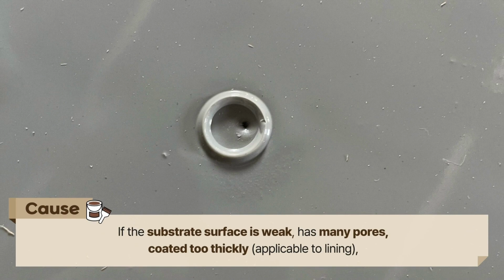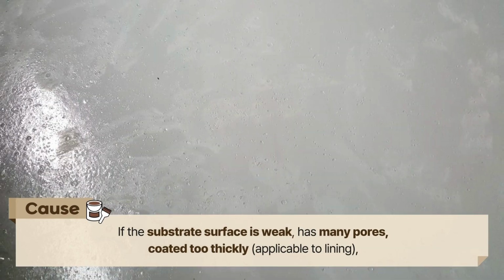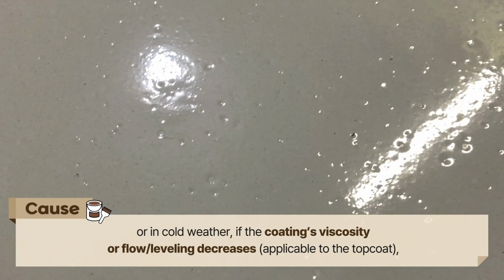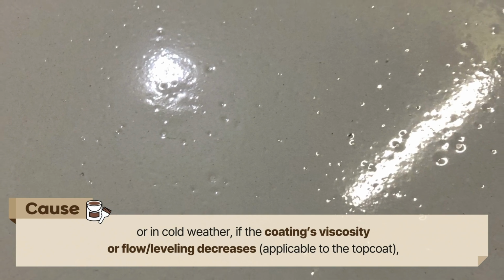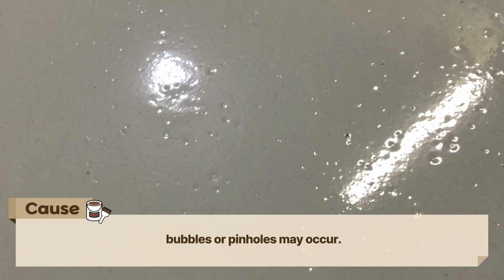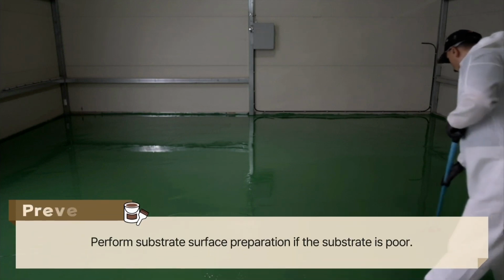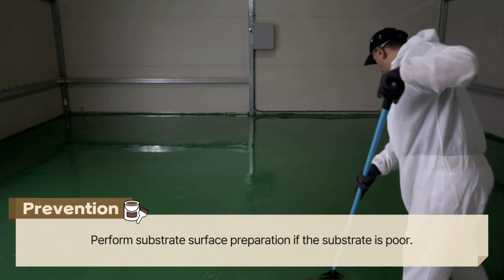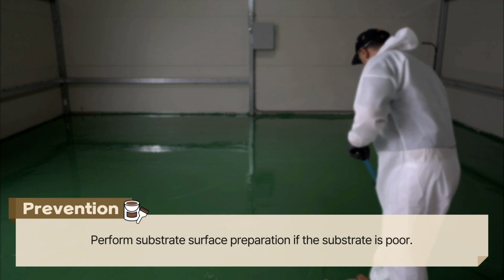If the substrate surface is weak or has many pores, or if it's coated too thick, or if the paint's viscosity or defoaming property decreases in cold weather, bubbles or pinholes may occur. If the substrate surface is in poor condition, perform surface preparation first.